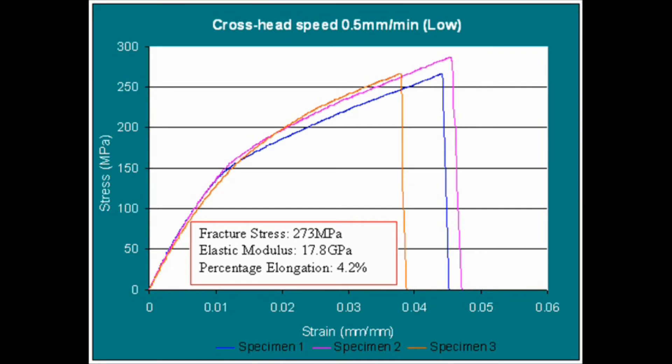This is the stress-strain curve for the test we have just conducted. The fracture stress was 273 megapascal and the elastic modulus was 17.8 gigapascal.